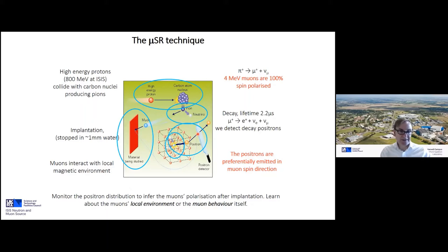Okay, so this is a really powerful technique, which is very sensitive to incredibly small moments. So for example, if you have a complex superconductor that breaks time reversal symmetry, where you might expect to get very small moments, much smaller than you can measure with neutrons, at the level of what you can measure with X-ray techniques like XMCD, then muons are a really powerful technique to study those sort of systems. And you can also do something interesting with things like battery materials, as we'll show.